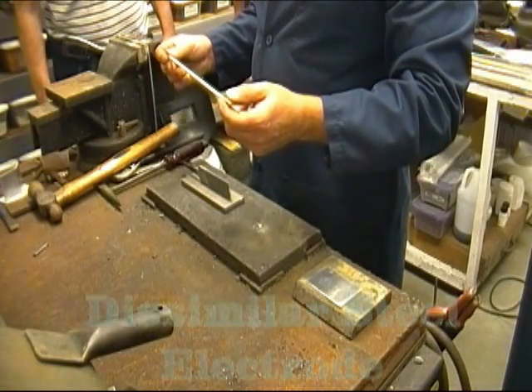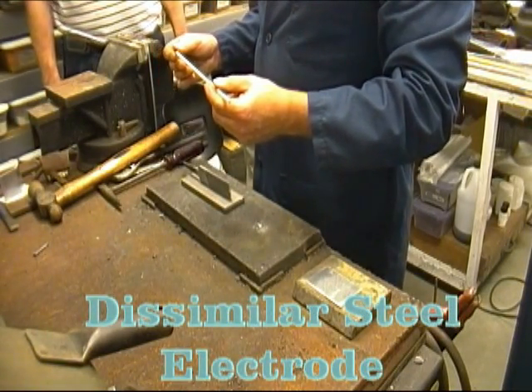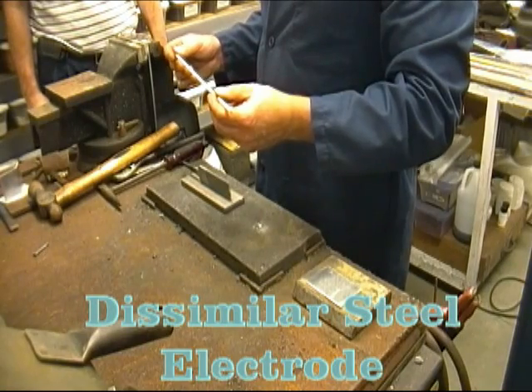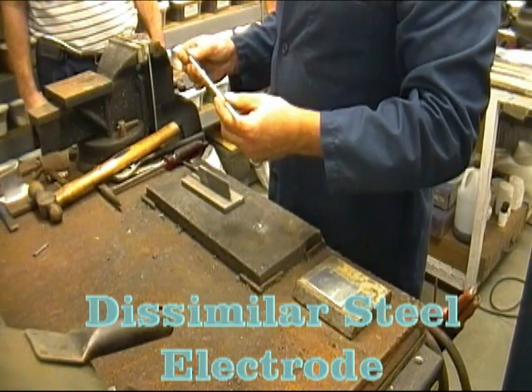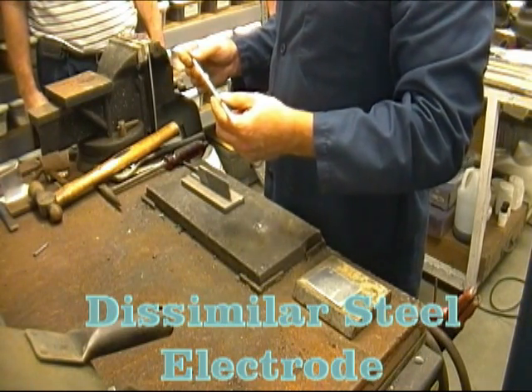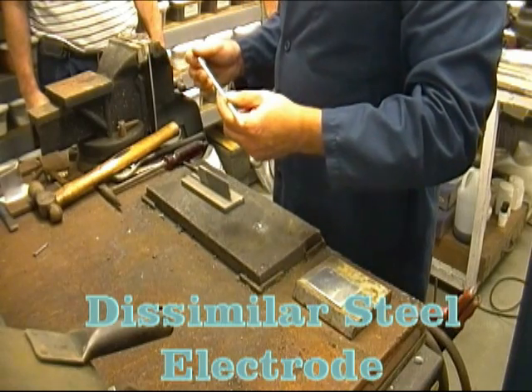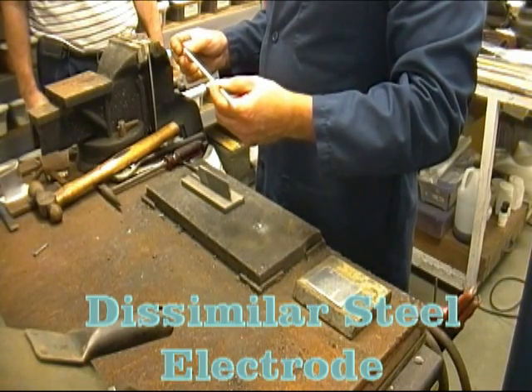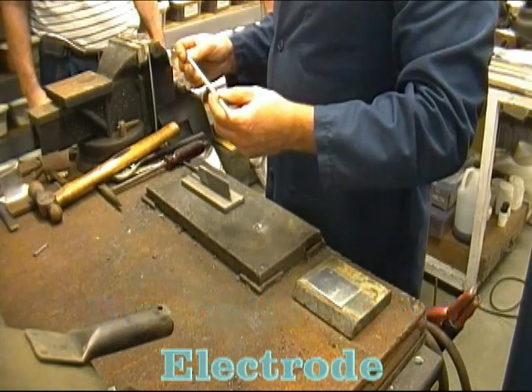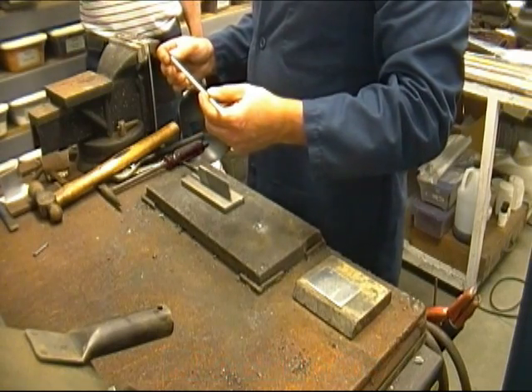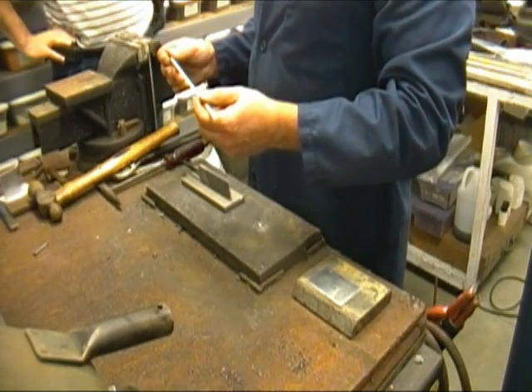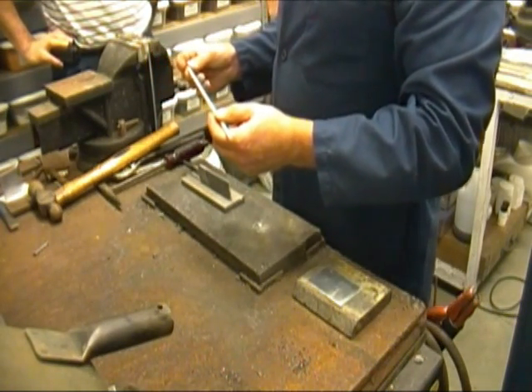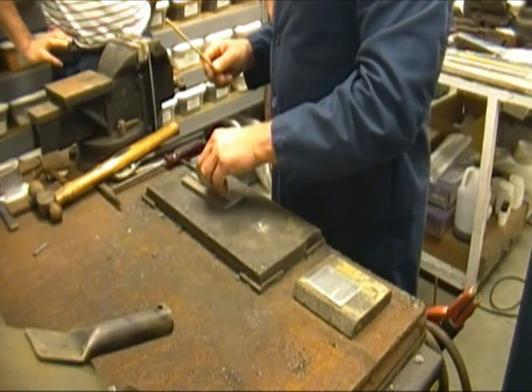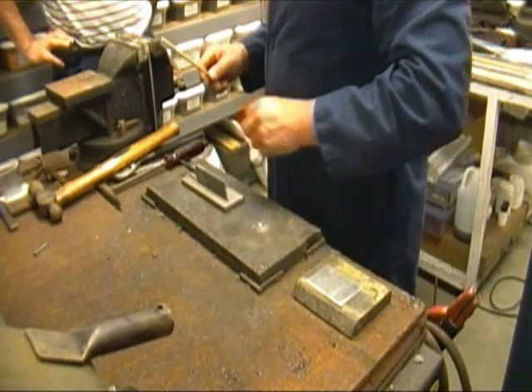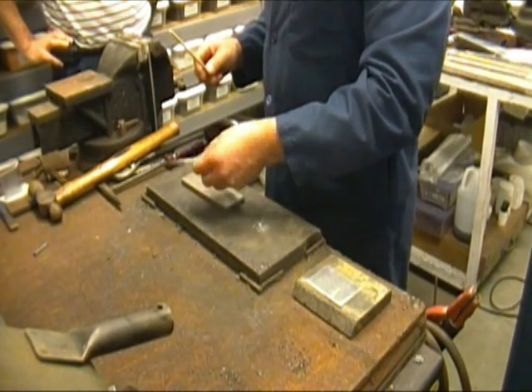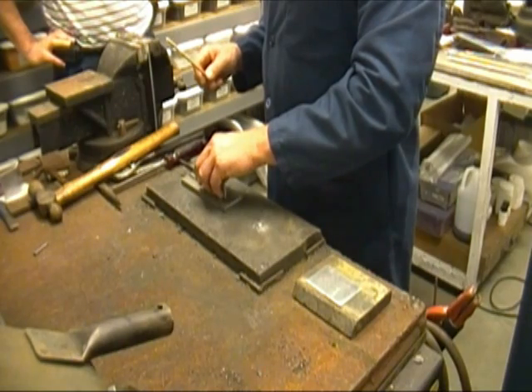Our dissimilar steel welding electrode. You can weld all steels with it, and also dissimilar steel combinations. It has a very high tensile strength of 128,000, and it'll work harden to 186,000 psi tensile strength with a very high elongation of 38%. Right now we're going to weld a piece of mild steel to a piece of high carbon steel, which is a piece of file, and we'll show you the strength of this.